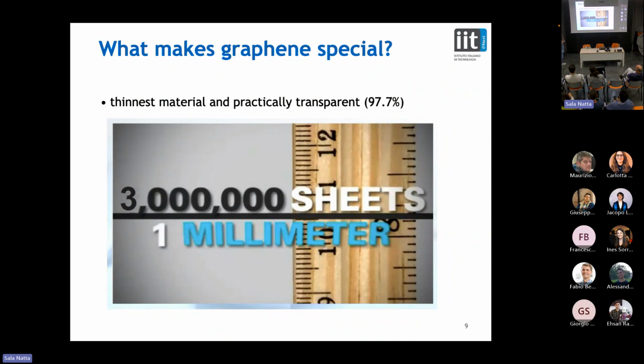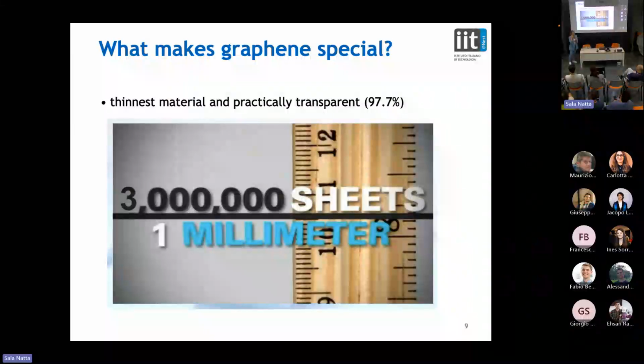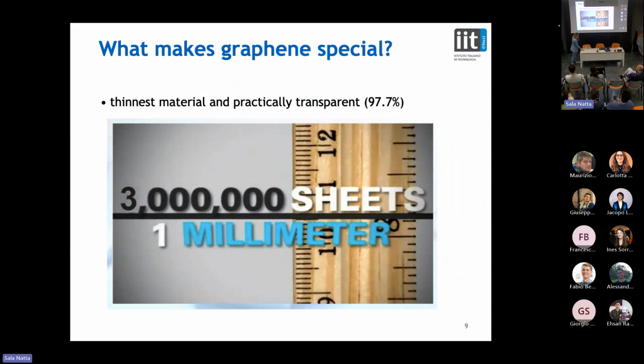Other properties of graphene. We talked about the electronics, so this incredible electrical conductivity. Then we also have a very interesting topological property, and that's where the story becomes interesting, because you have a mixture of different properties within one material. It's not only electronically interesting, but, of course, being the thinnest material, it is practically transparent because it absorbs only 2.3% of visible light. So indeed, it's not 100% transparent. If you put it on top of a proper substrate, you can actually tell with a very trained eye that there is graphene, but it's very, very thin.